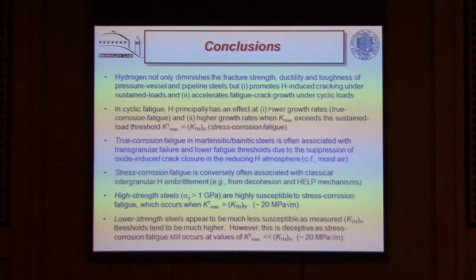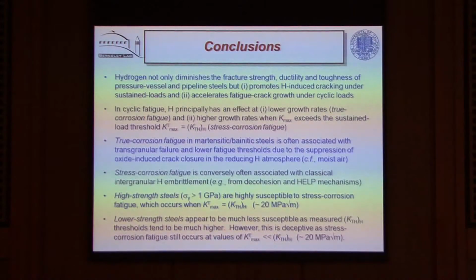I've talked about how there are different effects at lower growth rates versus higher growth rates, and the need to look not simply at the final fracture, but at the question of subcritical cracking. I've looked at how higher strength steels can show this effect very, very obviously, but it's also present in low strength steels. And in general, how there's a need here to fuse the scientific understanding of how hydrogen affects materials with the engineering need for actual data which can be used to predict the life and ensure the safety of our components that contain hydrogen. Thank you very much.